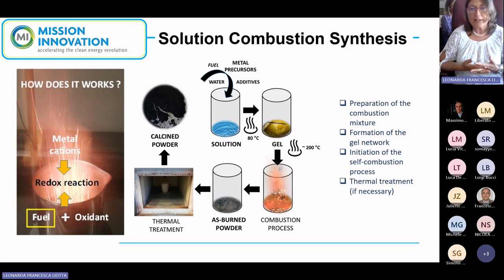That powder for us is very valuable because it's our final product. The preparation procedure is very simple. We have a so-called combustion mixture that can also be composed of solid materials, not only materials in solution. And we have, for example, a dispersion of silica together with other materials. So we have this combustion mixture. We regulate pH if necessary, and then we insert all the main components: fuel, oxidants, metal cations.